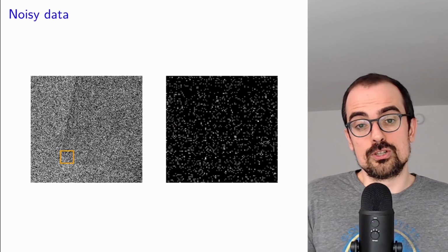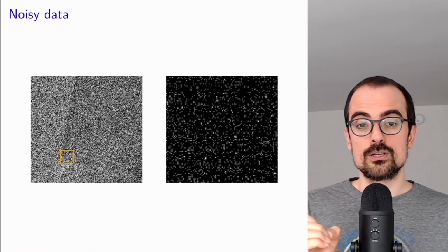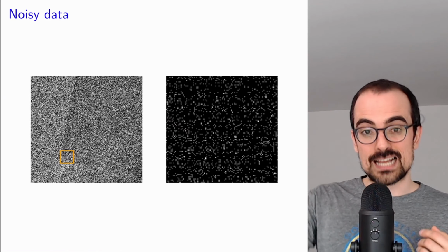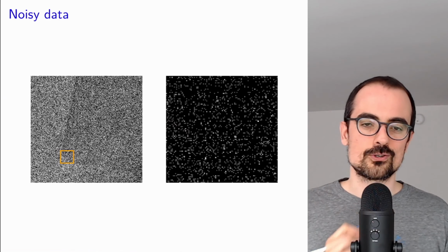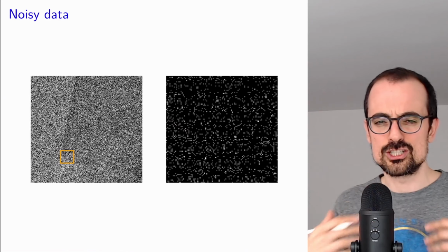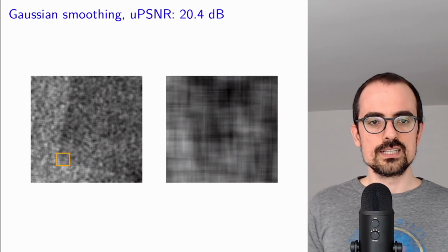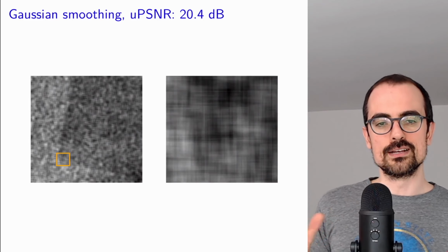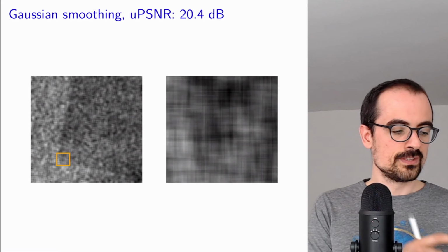So you're basically limited as to the electron dose that you can put into the material. The equivalent would be how much light you have when you're taking pictures. Here we would have very little light, very few electrons. And because of that, the data are super, super noisy. So this Gaussian smoothing, which is a linear shift invariant filter, does not do very well.